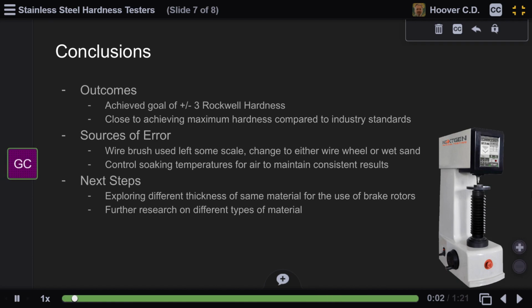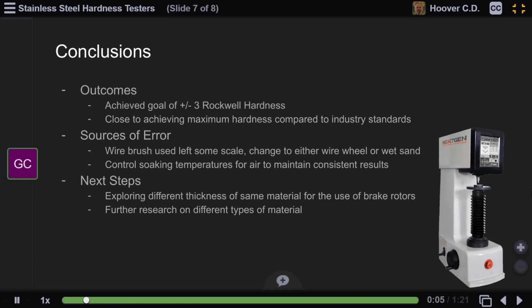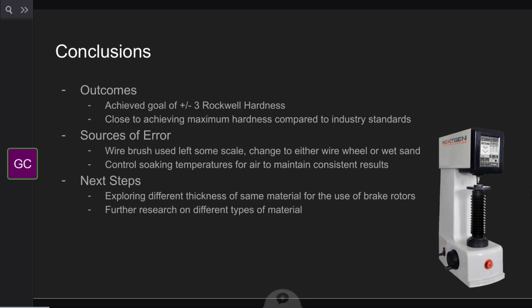After performing the experiment, it was safe to assume that we achieved our goal of plus or minus 3 Rockwell hardness. This goal was set to be close to the industry standards of our material. We ended up getting an average around C35 for hardness, when industry standard is about C38. The error of -3 could be a result of us using a wire brush. When we were testing it, some of the scale was still left on the material. To change this, maybe next time we can use a wire wheel, or maybe wet sand the rotors on a piece of granite.